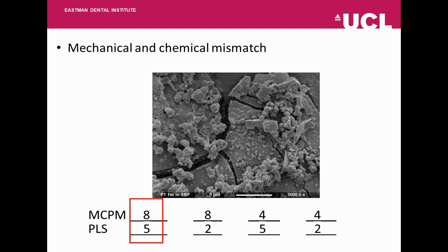Ultimately, the highest level of monocalcium phosphate and polylysine show the ideal physical appearance of hydroxyapatite after 1 month. And you can see that there was this layer on the disc and it's cracked, and you can see the ball-like features and also some needle plate-like features as well.